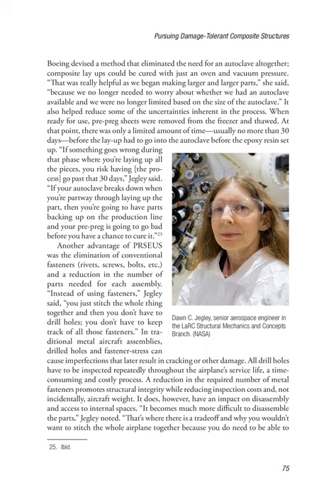The PRSEUS structural concept was made possible through advances in fabric manufacturing, out-of-autoclave resin infusion processing, through-thickness stitching technology, and single-sided stitching. Load path continuity at the stringer–frame intersection is maintained in both directions by passing the rod through a small keyhole aperture in the frame web. The presence of the rod increases local strength and stability of the stringer section while simultaneously enhancing the panel's overall bending capability. Frame elements, placed directly on the inner mold line skin surface, are designed to take advantage of carbon fiber tailoring by placing bending and shear conducive layups where they will be most effective. The stitching suppresses out-of-plane failure modes, enabling a higher degree of tailoring than would be possible using conventional laminated materials. This configuration results in a bi-directionally stiffened panel that is highly efficient in all three loading directions.